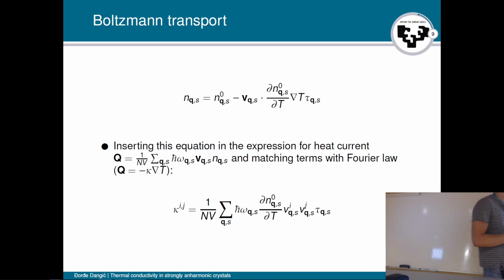And then by matching terms with the Fourier law, which we already showed, we can get to the expression of the lattice thermal conductivity in the Boltzmann transport equation. As you can see, we need phonon frequencies, phonon group velocities, and the phonon lifetimes to calculate the tensor of the lattice thermal conductivity. Now, how do we calculate the phonon lifetimes? We're not going to go into detail here, but one can use perturbation theory, first order perturbation theory, to get these phonon lifetimes. So this is what is implemented in most modern codes that calculate the lattice thermal conductivity.